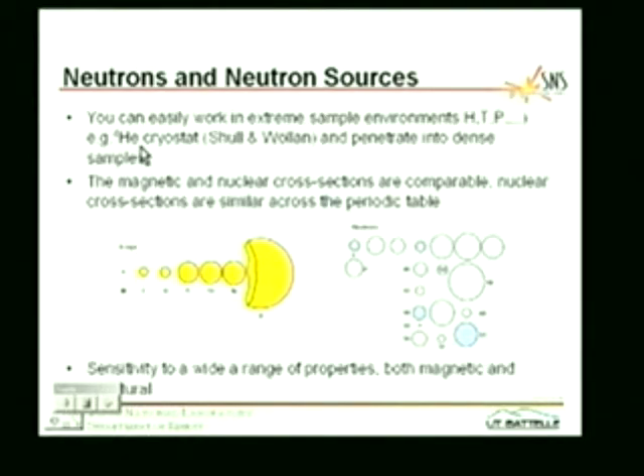And also you can penetrate into dense samples, so it's possible to do measurements deep inside intact engineering components. Neutrons will go through inches of steel and feet of aluminum and still be able to get out again with appreciable intensity. So if you're interested in measuring, for example, residual strains in intact engineering components, you can do that and do it in large real things as a function of position.